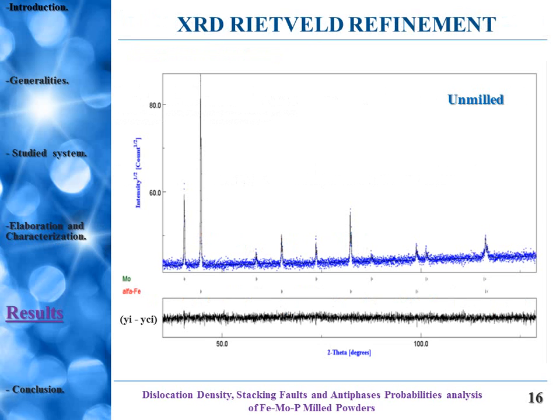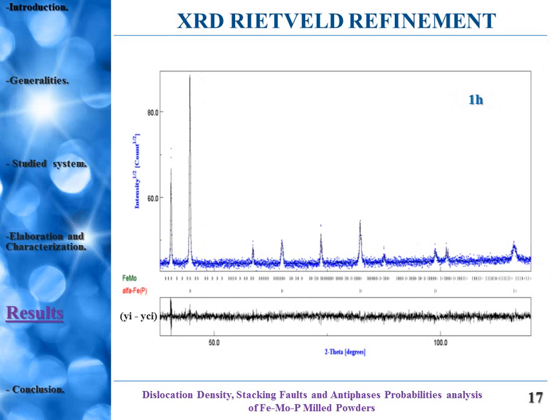We now turn to the results. Before the milling process, we note the existence of 2 different phases, which are the solid solution alpha and the molybdenum element, and the disappearance of the phosphorus element. After an hour of mechanical milling, we observed the disappearance of the molybdenum compound and the emergence of the iron molybdenum phase with the continued appearance of the alpha iron phosphorus solid solution.